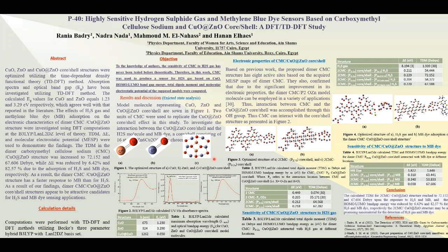As we presented in Figure 2, copper oxide and zinc oxide have sharp peaks at 675 and 324 nanometer respectively as a dominant transition, which is shifted to 1000 and 262 nanometer for the core shell structure. The large shift in the absorption peak confirms that the molecular structure of copper oxide was changed due to the formation of zinc oxide layer. Table 1 shows the maximum absorption wavelengths and the optical band gap energy of the three structures. As indicated in the table, the optical band gap of copper oxide zinc oxide core shell structure is lower than that of copper oxide and zinc oxide, and this is due to the formation of localized states within the band gap.